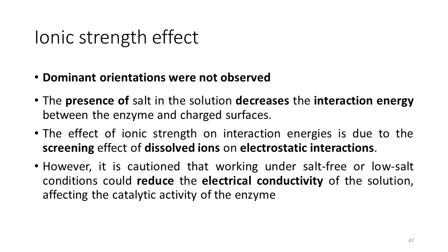However, one of the problems is that I got very good results of absorption of the protein in simulations without salt, but in real life, if I want to apply this technology to absorb hydrogenases on the surface of the electrode in electrochemical devices to produce hydrogen, I'm going to need some salts in the solution. One reason is that I need to maintain the physiological concentration of salts in the solution to keep the hydrogenase functional.